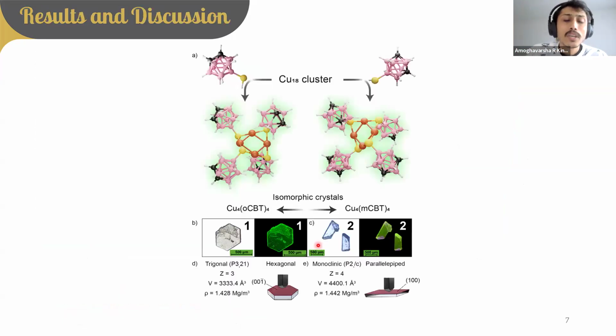Now, directly jumping to the results and discussion, here I have shown how we have synthesized these nanoclusters. First, we have synthesized a phosphine protected copper 18 nanocluster, and to that we have added orthocarboranethiol and metacarboranethiol, both of which differ only in the position of the carbon atom in the structure. They both form copper 4 nanocluster with a shape of the core like this.